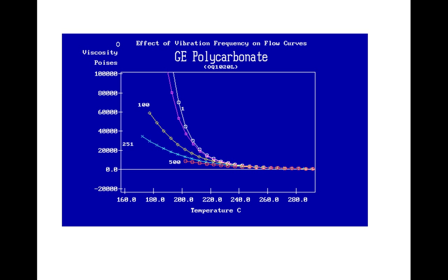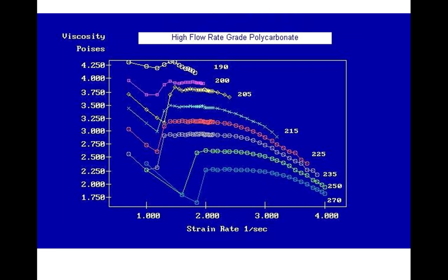Quickly browsing through the next slide, which describes the apparent viscosity versus the apparent strain rate without any type of correction in the case of a capillary flow. This is the same grade — a high flow grade, MFI equals 65 — from General Electric polycarbonate grade used in the production of compact discs, CD-ROMs, and other visual support devices. This is plotted as a log-log plot. Same tendency for viscosity to plateau in the Newtonian region when plotted versus omega or when plotted versus the strain rate.